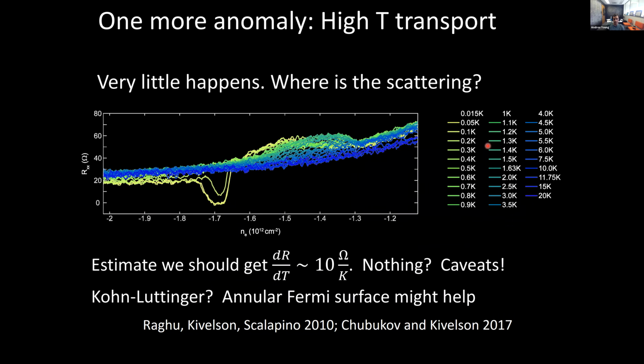One more anomaly that I'll present just as food for thought is that at high temperatures, very little happens. In other words, we can increase the temperature here above the superconducting transition. This is again as a function of density, and the resistivity really doesn't do very much. It sort of stays about the same up to 20 Kelvin, and that is surprising because